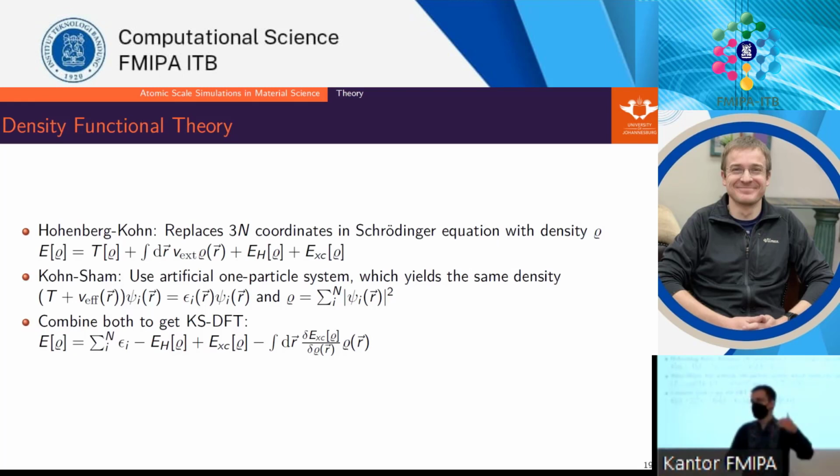All right. The results I present here in any way are based on density functional theory, which is basically a reparametrization of the Schrödinger equation, making two assumptions. Assumption one, I don't need the 3n coordinates of my electrons. I just need a function rho of position r in space that will describe my electron density, and that is sufficient. I don't need to track every electron. I just need the electron density. Electrons anyway are supposed to be delocalized most of the time. So yeah, that sounds fair. And that is exact, it's not an approximation, that's an exact rewrite. So we're happy with that.